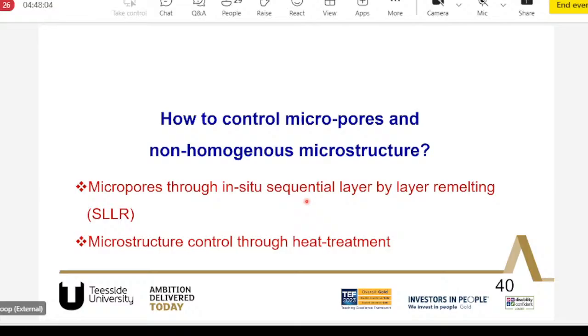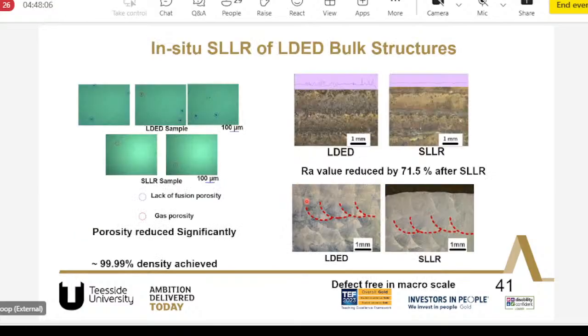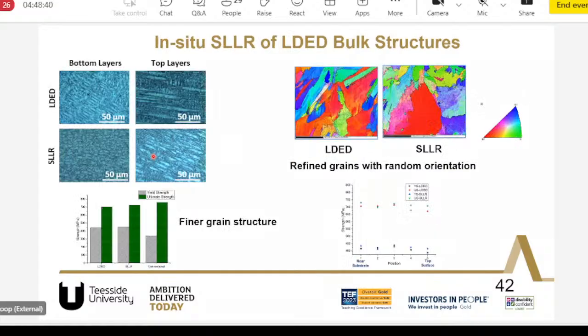One of the studies we recently published is on sequential layer by layer remelting, where we used SLLR as a process to remelt the material during the manufacturing. And then we could reduce the porosities, we could improve the surface quality, and at the same time, we could homogenize the material. You can see that surface roughness reduced significantly, the porosities were reduced significantly, all the lack of fusion porosities that formed in the material got reduced significantly, and we could achieve high density. Also, we could refine the grains to some extent.